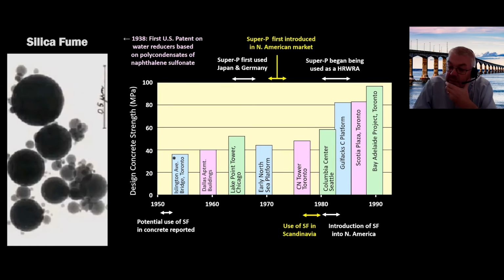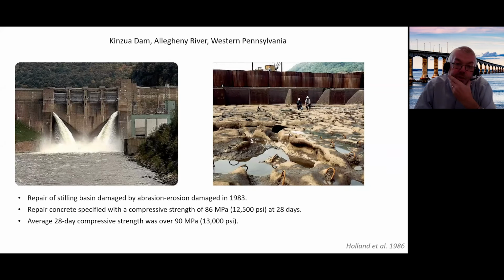Silica fume didn't appear in North America till the 1980s. Its potential for use in concrete was known as early as the 1950s. It didn't get widely used in Scandinavia till the 70s, and then not really in North America till the 80s and beyond. One of the first uses, a major use in the US, was in the repairs to the Stilling Basin of this dam in Pennsylvania, where 86 MPa, 12,500 PSI concrete was specified for its high abrasion and erosion.